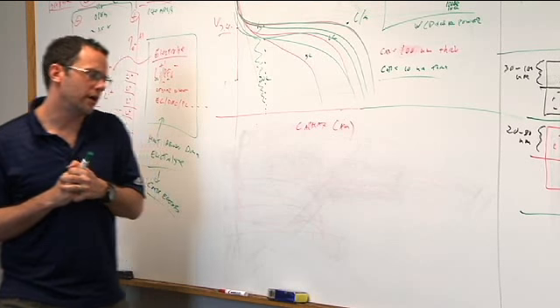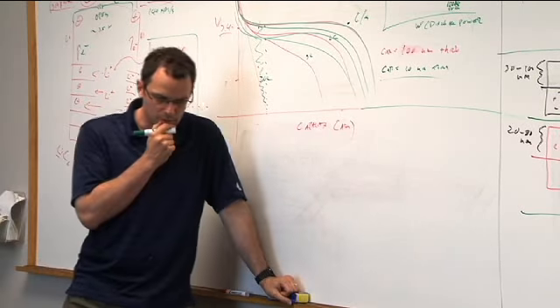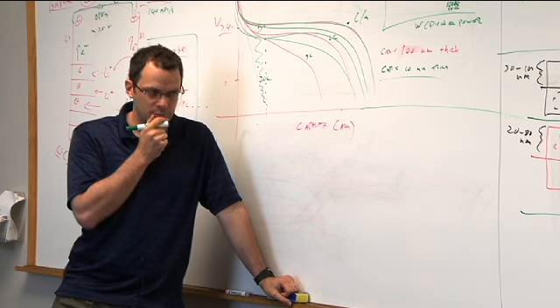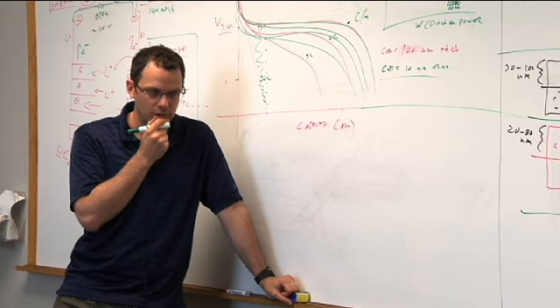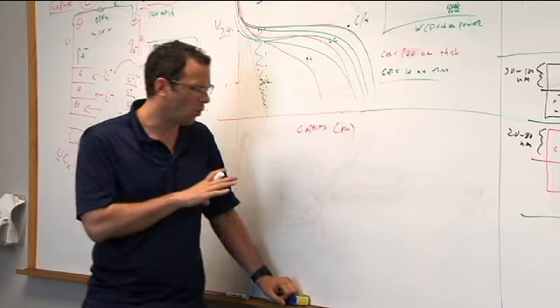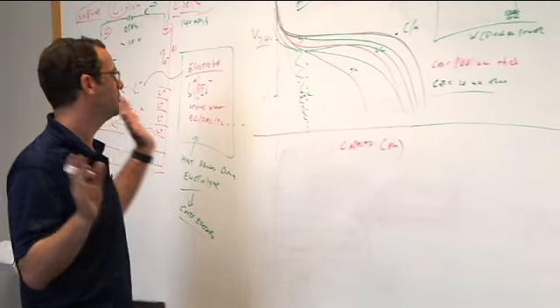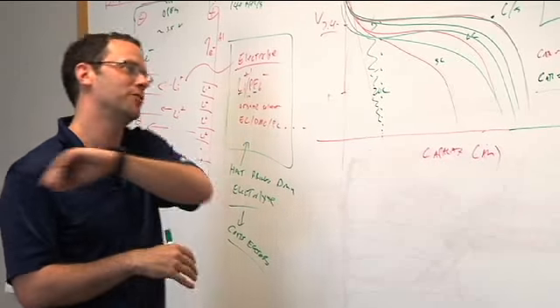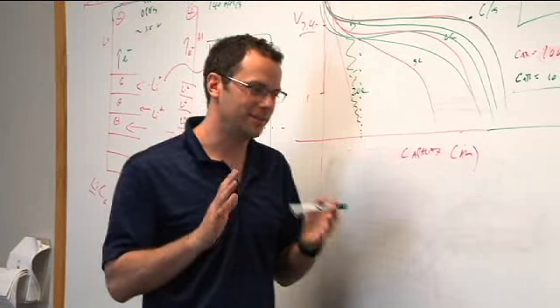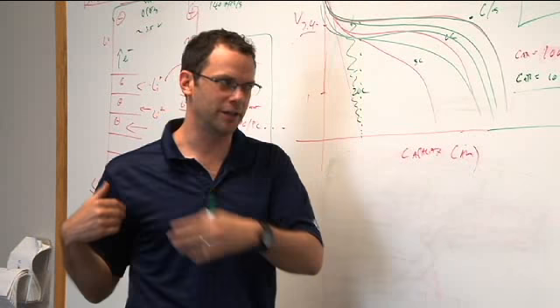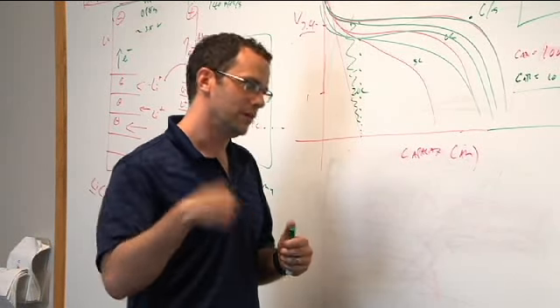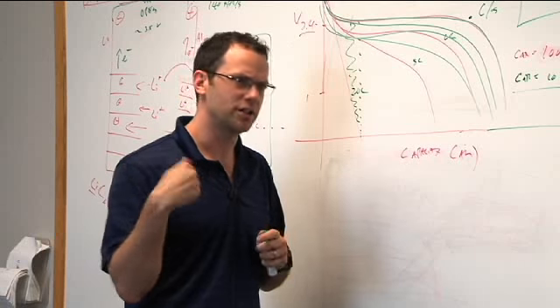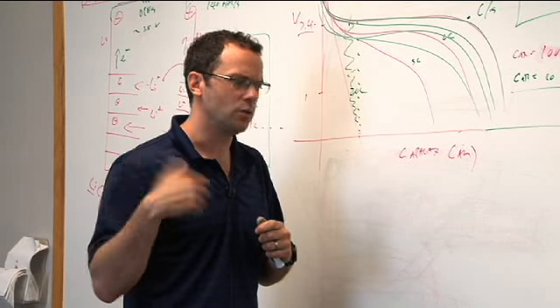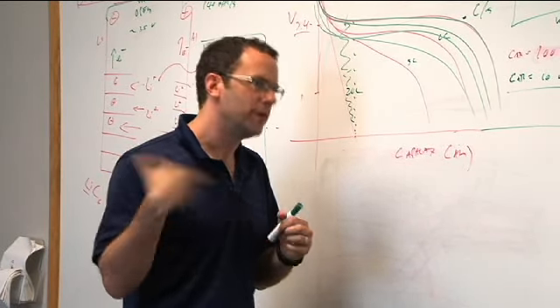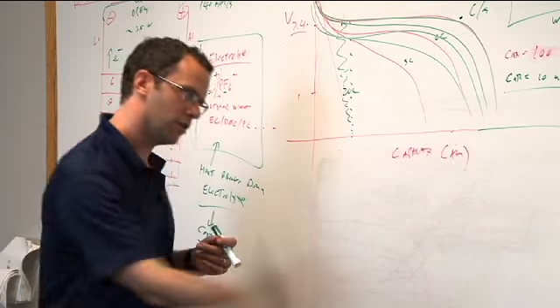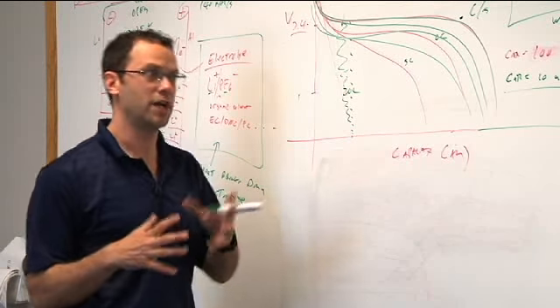There surely is, and in fact, there are a couple of really interesting proprietary and/or patented charging techniques. Lead acid as a whole is so different. It's not even the same. All the chemistry is different. All the problems are different. But that being said, lead acid builds up these sulfate layers on the electrodes, and it turns out that when you do much higher frequency charging, almost AC charging, you end up cleaning and stripping that sulfate layer more efficiently than if you just have a constant current charge.